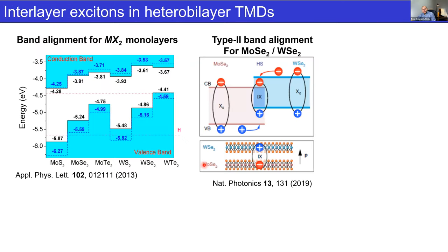And with any combination of two TMDs, any heterostructure of two TMDs, one ends up in a type 2 band alignment. So it doesn't matter which ones you choose. So for molybdenum diselenide and tungsten diselenide, the band alignment looks like this. So if you excite electron hole pairs in the system, the holes will quickly relax to the tungsten diselenide, and the electrons quickly relax to the molybdenum diselenide layer. And this creates what we call an interlayer exciton that has a large permanent dipole moment that perhaps we can take advantage of.